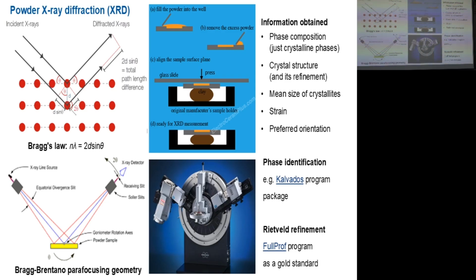So what information is provided by powder XRD? As I mentioned, this is the principal method to analyze the phase composition. So you can determine the crystalline phases present in the sample, but just the crystalline phases. You won't see amorphous components because they don't provide this kind of diffraction. They don't have any Bragg diffractions. Of course, you can analyze the diffractogram to determine some crystal structure parameters. But typically this is used when you already know the crystal structure, or you suppose a certain crystal structure, and you are just determining certain parameters of it. So basically, you are refining the crystal structure.